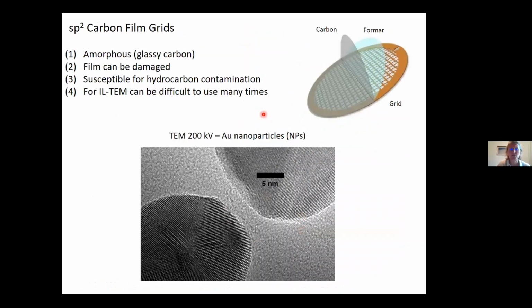You can do this on the carbon films as I've shown you. TEM grids, they're so thin. It's like a film of glassy carbon that's floated onto the surface. So people are using these as electrodes. It is difficult though to work with them. And for identical location TEM, you have to put in, take out, put in, take out. So you need to be careful you don't contaminate in any way or you damage the film. They can rip and tear. And sometimes they're not as robust as potentially you would like. I don't think this video is going to play unfortunately, but it would have shown you these two gold nanoparticles, under the influence of the electron beam, coming together on an sp2 grid, and you would have seen a big hole opening up in the background.